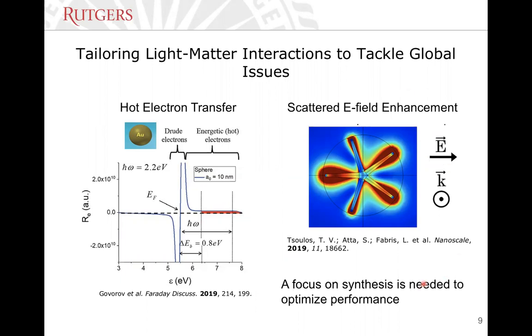And on the other hand, because we are interested in surface enhanced Raman scattering, these nanostars can be really relevant because upon absorption of light, they can scatter the electric field, and this electric field can be substantially enhanced. As you can see here, this image is a 2D slice of a 3-dimensional finite element model that we ran on these nanoparticles, which have 5 spikes in plane and 2 perpendicular spikes coming in and out of the plane of the screen.